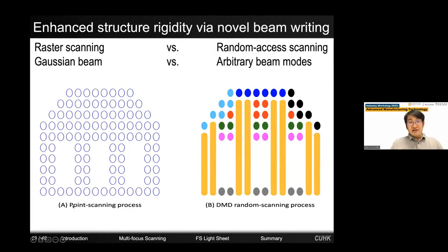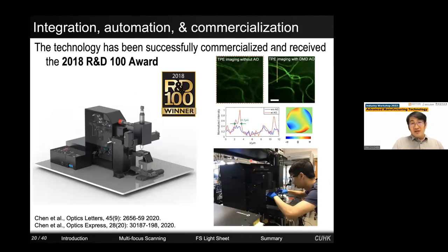Okay, so here we briefly compare the difference between the conventional process and our random access scanning process using this 2D pattern. In the raster scanning conventional process, the laser has to be scanned layer by layer. So even if you have empty spots, you have to scan through them and just turn off the shutter. In our process shown on the right, each color represents one exposure, so we can expose multiple points simultaneously. We can build these pillars through a different beam mode, for example, the Bessel beam. So as a result, these empty spaces, we don't really need to go there. Based on this principle, we increase the fabrication speed by around two orders of magnitude compared with a point scanning process.